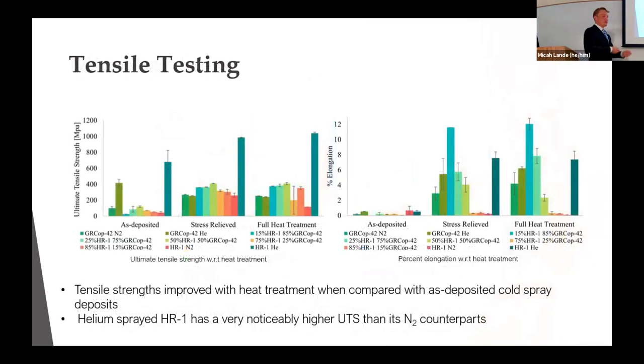So then after the microhardness testing, going into tensile testing, these graphs are laid out the same, where we go from left to right through the heat treatment process, and then also left to right in each step, we have our higher copper content to our higher HR1 content, and then mixtures in between. In the ultimate tensile strength graph here, these peaks that you see, and especially this one carrying throughout, those are the helium spray ones, which, as I said before, we can now visualize the benefit of using helium sprayed rather than nitrogen sprayed, because all of those particles being more bonded together, more squished together thanks to that extra velocity, they're able to retain much better physical properties. And so especially with the HR1 solid, that was tremendously strong stuff.